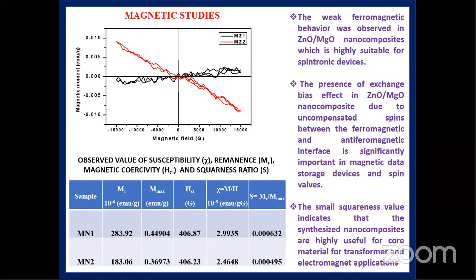And then we performed the magnetic properties of this nanocomposite. For the nanocomposite of two different ratios, weak ferromagnetic behavior was observed, which could be useful for spintronic devices. You can see the presence of the exchange bias effect in the zinc oxide MgO nanocomposite due to the uncompensated spins between the ferromagnetic and antiferromagnetic interface, significantly important in magnetic data storage devices and spin valves.